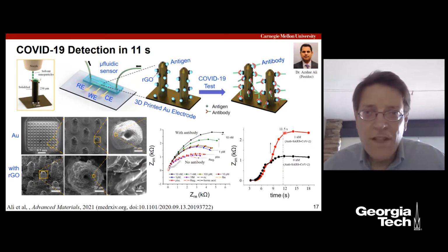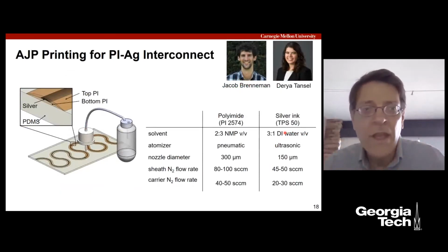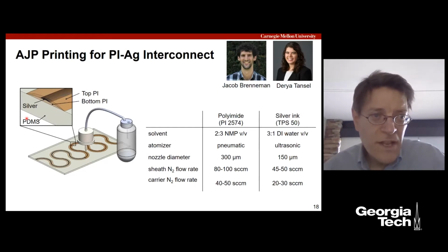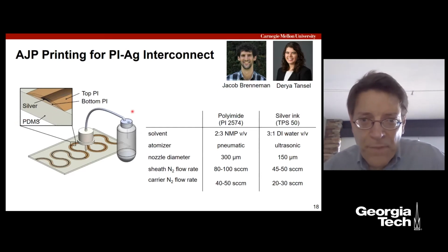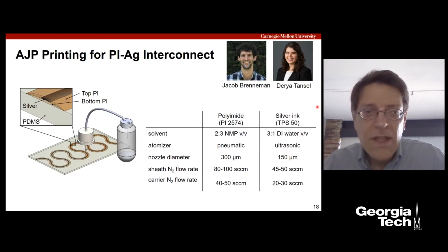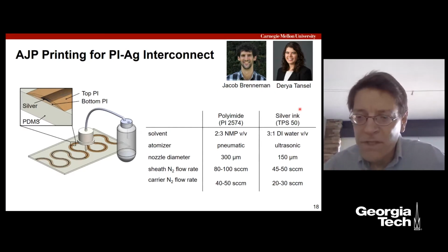So that's kind of an introduction to aerosol jet, and so what are we doing? We've got a couple of grad students, Rahul's student Jacob Brenneman and my student Derya Tansel, teaming to do polyimide silver interconnect on PDMS. You can see the setup here in the upper left with a polyimide that's dissolved in NMP using the pneumatic atomizer. For those of you that are interested, these are the settings. And then using a silver ink from Clariant that is commercially available and diluted with DI water in the ultrasonic atomizer. So this 3D printing is done serially, layer by layer, to build up these structures.